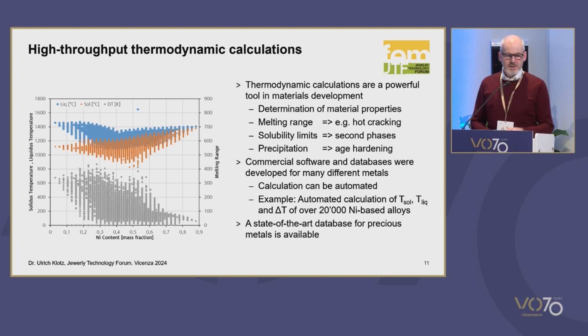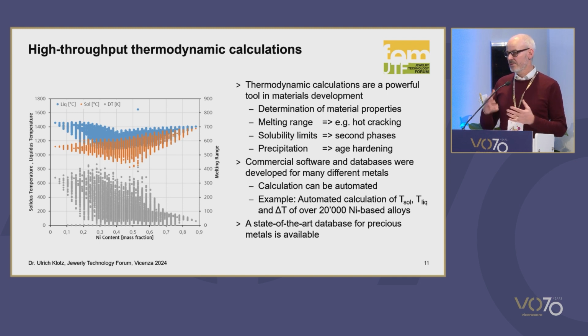Now we can also do the calculation of a solidus and the liquidus range, for instance. And this is an example I prepared for nickel-based alloys. These were alloys with up to 8 components based on nickel. And we wanted to vary the alloy compositions to find alloys with a suitable melting range, with a certain amount of phases. And so I used the high throughput calculation technique and calculated 20,000 alloy compositions. And this plot is showing the results. So you see that the solidus, the liquidus temperature, and the melting range are varying in a quite wide range.